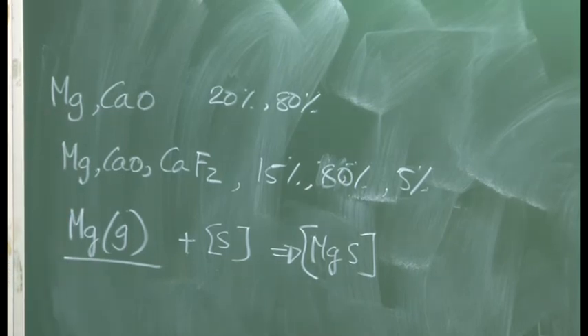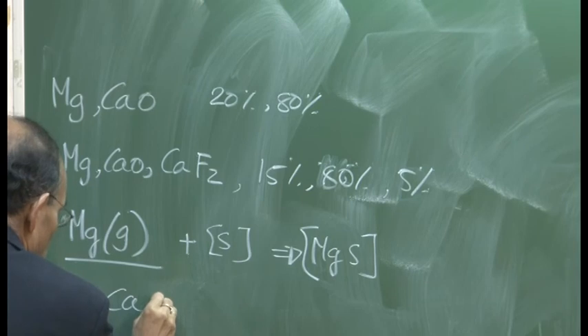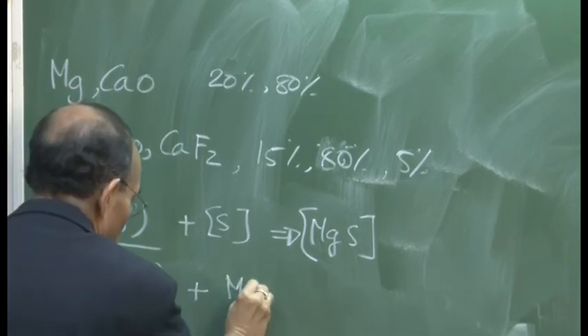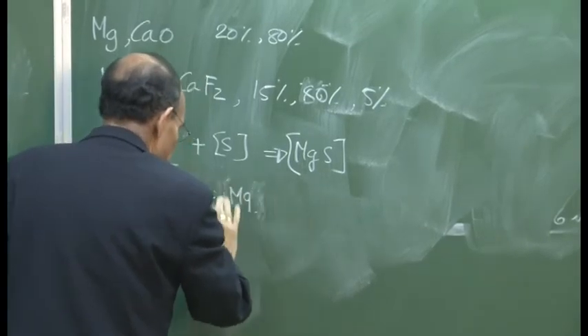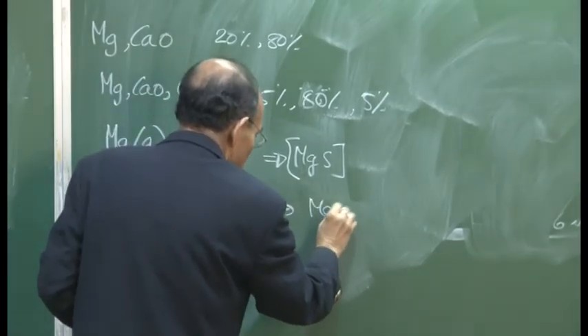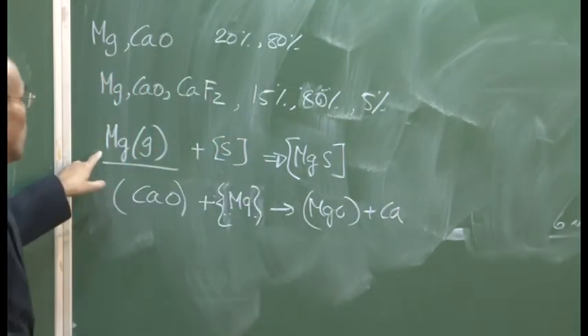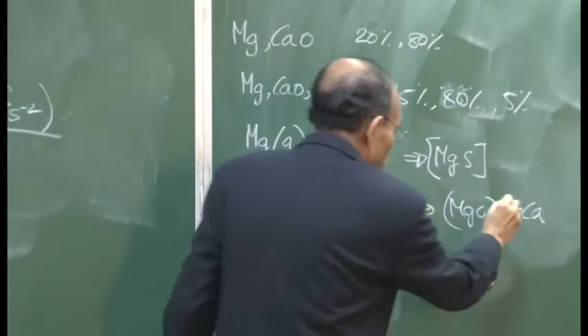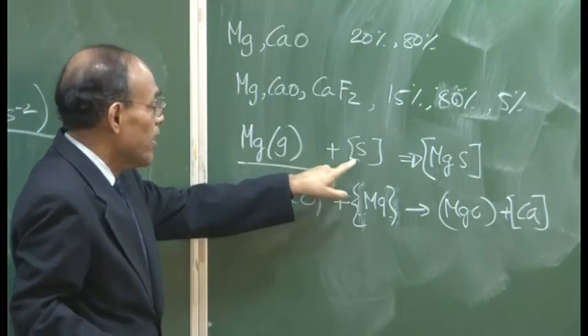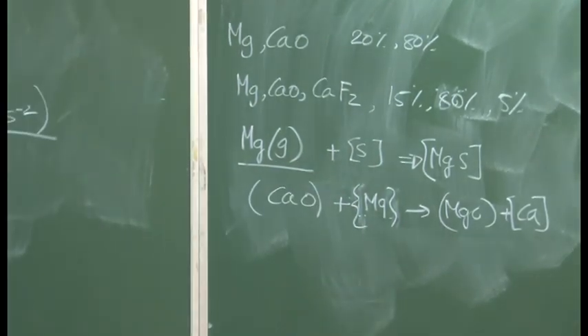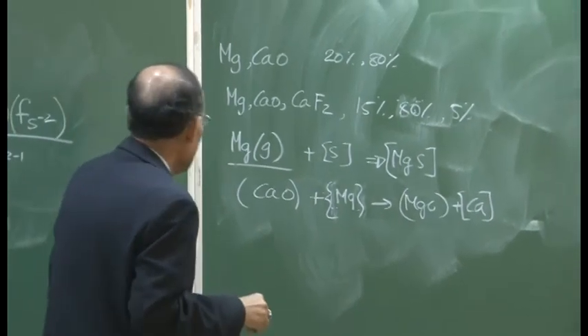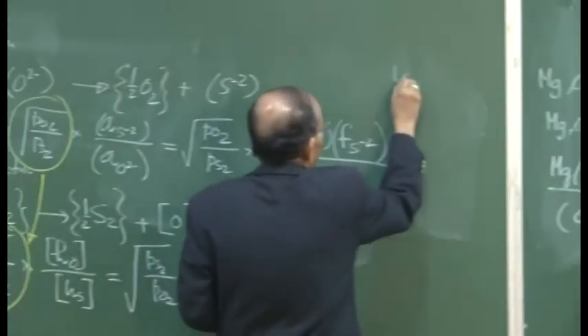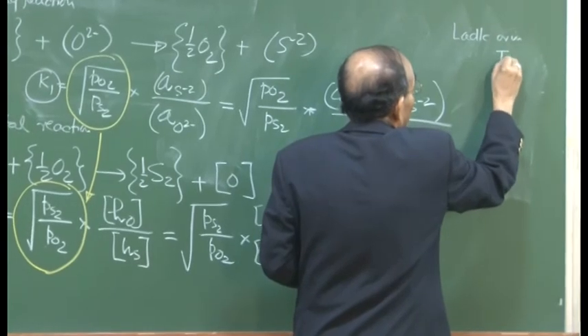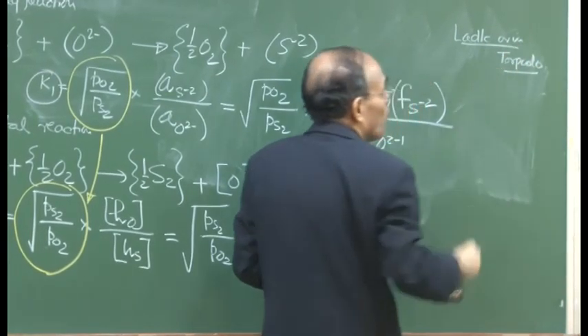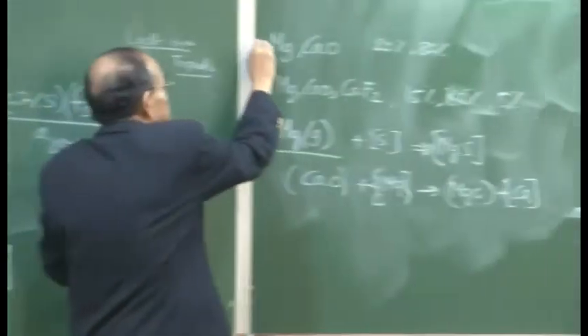Similarly, calcium oxide can react with magnesium, and this is gas actually. So I would write this, and that gives rise to magnesium oxide and calcium. This is a dissolved calcium, of course, and that dissolved calcium can take part in accordance with the same equation and cause desulfurization. Now, desulfurization is also carried out either in ladle or in torpedo vessels. Desulfurization, as we see, will be carried out by addition of these reagents.